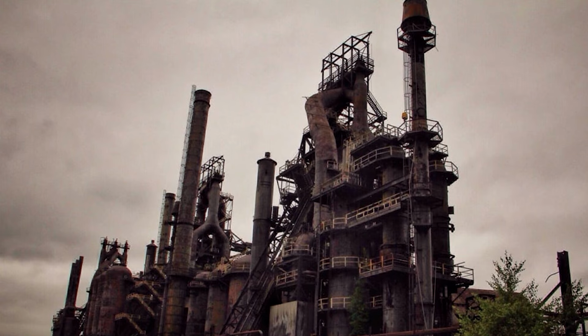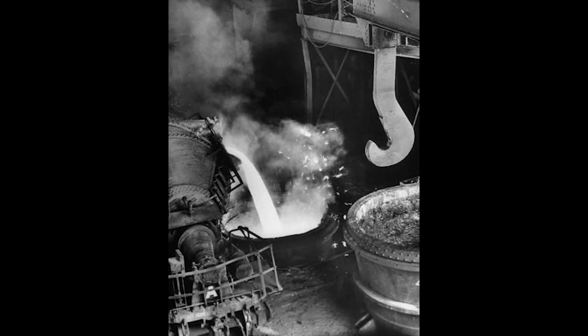The plate soaked at tempering temperature for several hours. Temperature control was critical. Too hot, and the steel softened excessively. Too cool, and brittleness remained. After tempering, the plate air-cooled to room temperature. The final product was rolled homogeneous armor with properties that could be measured precisely. Brinell hardness testing involved pressing a 10 mm hardened steel ball into the armor surface under 3,000 kilograms of force, measuring the indent diameter and calculating hardness from the indentation.